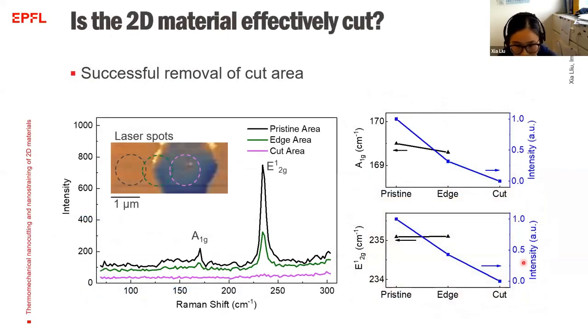So I think you may ask if the 2D material is efficiently cut. Maybe you just didn't cut it, you just bent it. So we did some Raman spectra on the samples, on the pristine area, some edge area, and the cut area, based on the Raman intensity. You can see the intensity of the cut area is almost zero. It means there is no material in this area, and the cut area is successfully removed. This is the single spectral measurement.